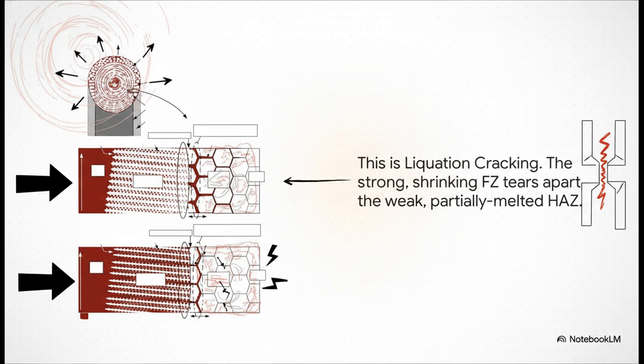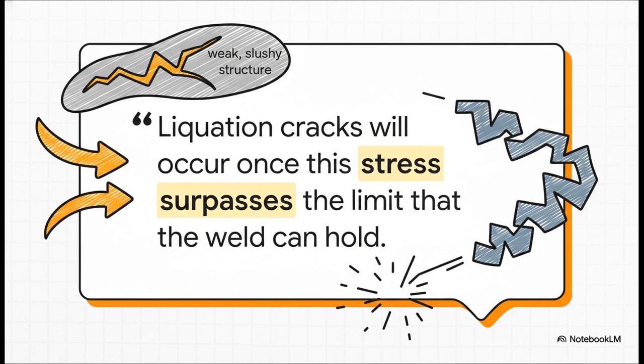This diagram shows it perfectly. On the left, you've got the fusion zone. It's solidifying, it's getting stronger, and it's shrinking. As it shrinks, it pulls on the HAZ right next to it. But look, the boundaries between the grains in the HAZ are still partially liquid, kind of like slush. They have zero strength. So that powerful pull from the solidifying weld literally rips the weakened grain boundaries apart. Yeah, it really just comes down to simple physics, you know? The stress from that shrinking weld just keeps building and building until it overpowers the weak, slushy part of the HAZ. And once it does, snap, a crack is born.